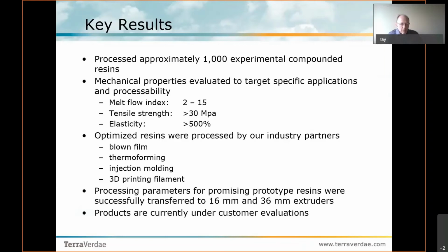We were able to document mechanical properties for the various applications, which I'll talk about more in a minute. We had resins with a melt flow index from as low as 2 up to 15. Tensile strength, we could get up over 30 megapascals, and for elasticity, we achieved the elasticity for blown films. That was the main target of greater than 500%. And I think when we transferred that to larger scale, the properties improved past that.